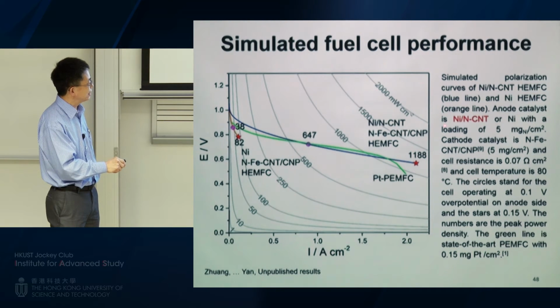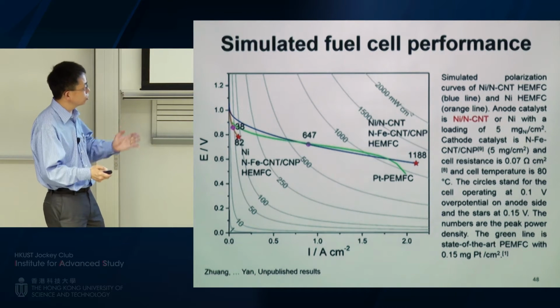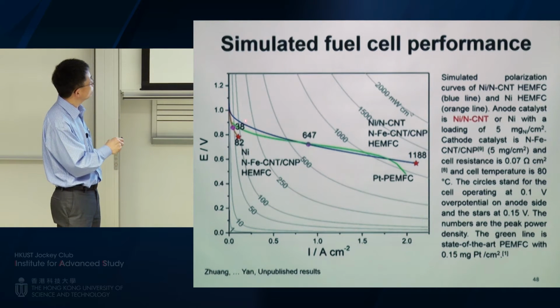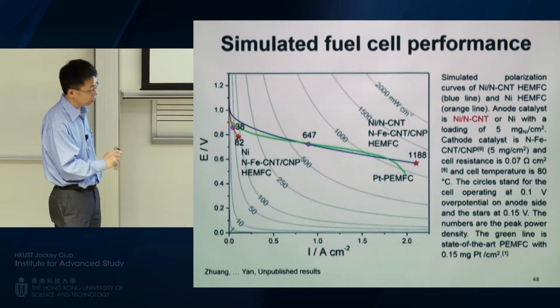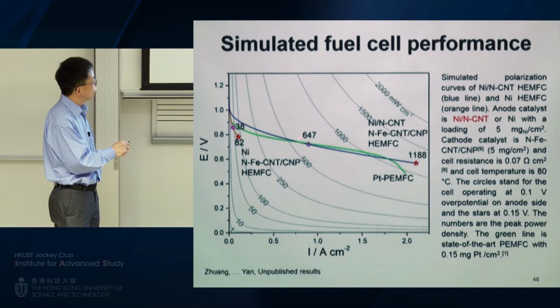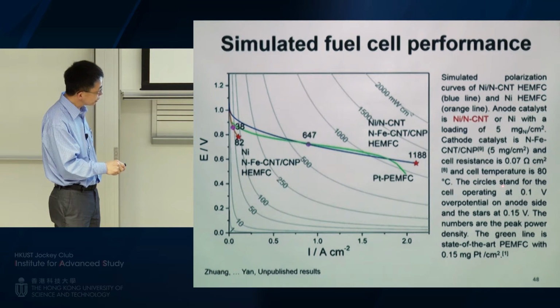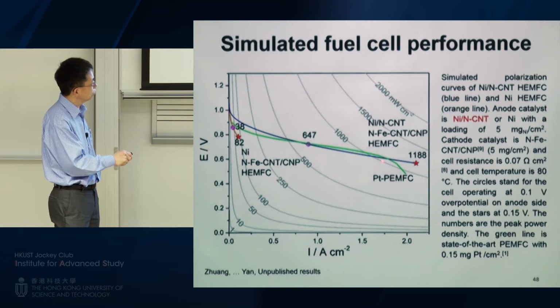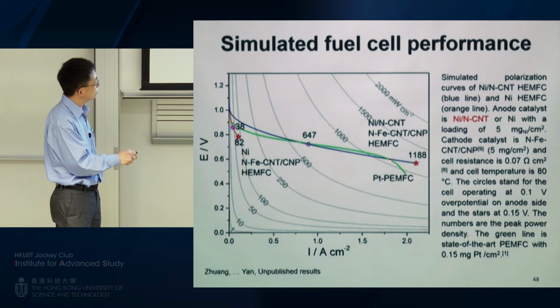We only have rotating disk data. This is not in the MEA, so we know the Butler-Volmer potential-current relationship, so I can do the simulation. What you can see is the green curve can actually match the blue curve. So this is the important message. If you allow only 0.1 volt overpotential applied on the anode on nickel, you can reach 647 milliwatt per square centimeter. This is here. If you can afford to have 0.15 volt overpotential on nickel, you can actually get here. This is actually much better.